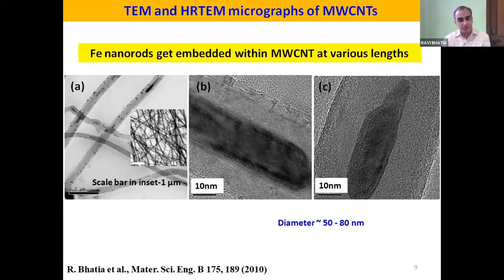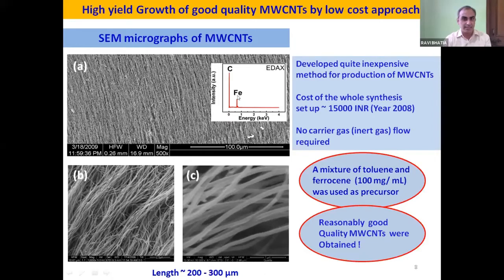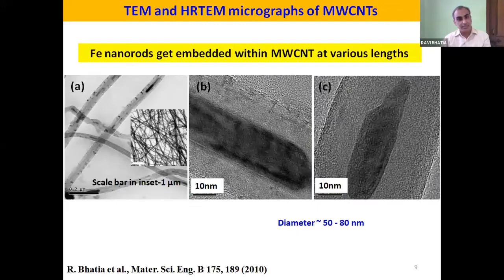Anyways, I just told you that once we prepare a sample, we must thoroughly characterize it first. So in the same sequence, we carried out HRTEM and TEM measurements. I told you the EDX gave us a clue that there is iron present in the carbon nanotubes, which cannot be seen through an SEM micrograph, SEM microscope. So we need to do this characterization using TEM and HRTEM. Clearly, there is a black particle present in this figure A, which was further seen using HRTEM, high resolution transmission electron microscopy, and one can see first thing that there is the black particle present within the carbon nanotube, an iron nanoparticle.